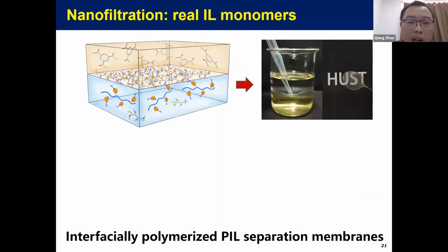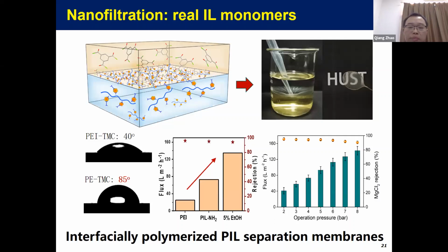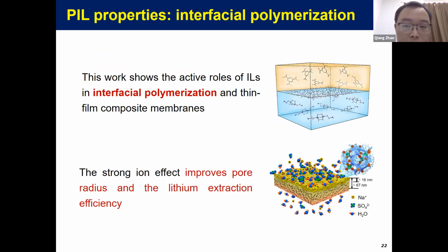And the last slide of my talk is about polymers. We have ionic liquids. We also use poly ionic liquids. The poly ionic liquid, when used as an aqueous monomer, features very good advantages to prepare thinner membranes, such as 30 to 50 nanometers. These membranes also show very high permeability combined with good selectivity. With all this, I would like to come up with a very brief conclusion.